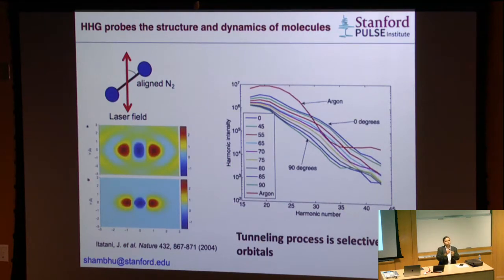And if the target was a molecule, molecules typically have interesting geometrical structure, right? If it had some interesting geometrical structure, as shown here, a very simple diatomic nitrogen molecule, right? Then, depending on which direction the electron actually came back to, it's going to see the molecule differently, right? So it's sort of like you're taking the selfie. You're sending the electron out, and then the molecule is taking its own selfie. Okay, and in the experiment, what you measure is the angle dependent. You align the molecule and measure the angle dependent high harmonic emission. Basically, the efficiency of the generation as a function of different angles, and you compare this to some isotropic medium like atom, and you come out with this beautiful picture of the orbital that might remind you, even if you took modern physics or early quantum mechanics.